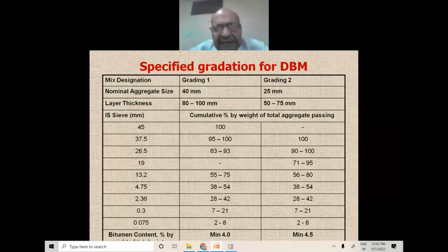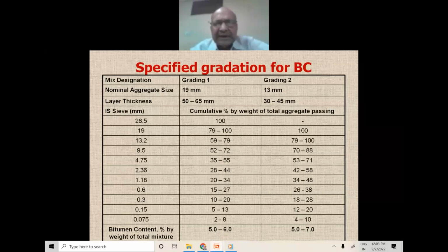Marshall quotient is very important nowadays. Majority of the vehicles are carrying excess weight and excessive tire pressure. So, due to excessive weight and excessive tire pressure, the deterioration of bituminous surface is faster. So, the Marshall quotient becomes very important and its value should be between 2.5 to 5. Air voids 3 to 5. Voids filled with bitumen 65 to 75. Coating strength ratio 90% minimum.